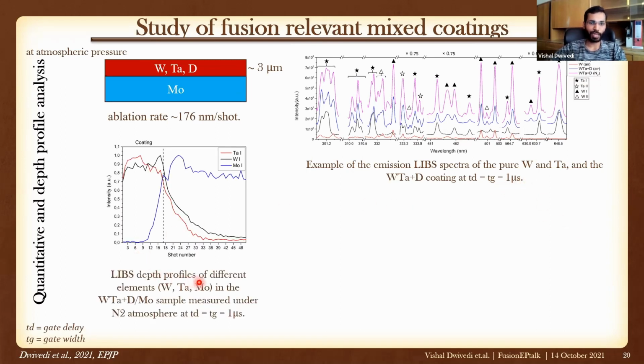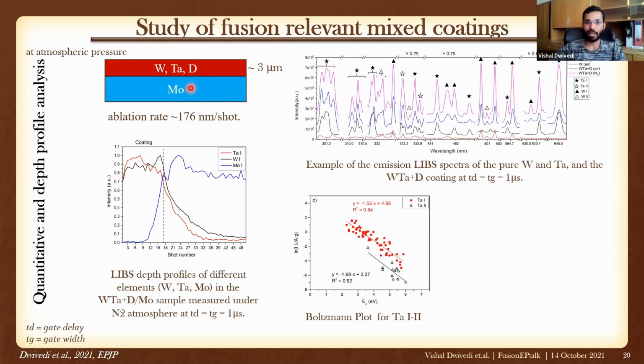We have LIBS depth profile also. So tungsten, this black one, molybdenum, and tantalum. So after 17 shots, we see that it started decreasing. So we are approaching the substrate here. And this was the Boltzmann plot for tantalum lines. We have also for tungsten. It is reported in the paper.